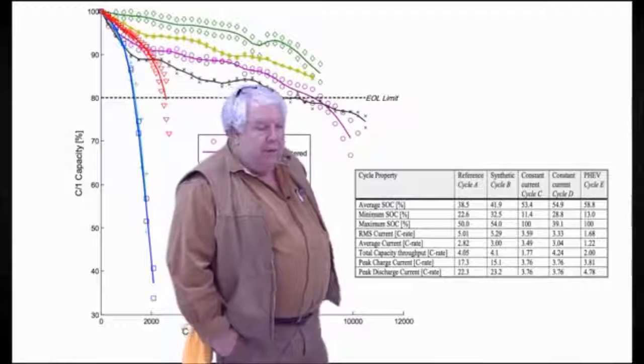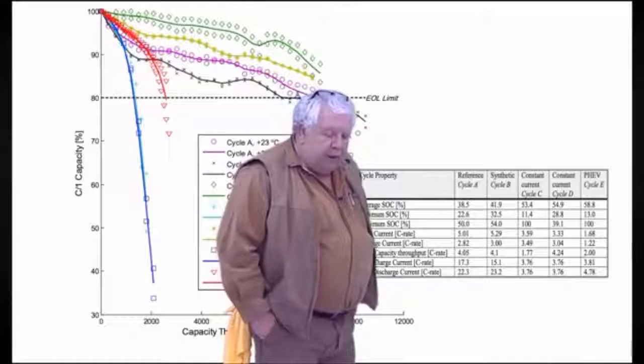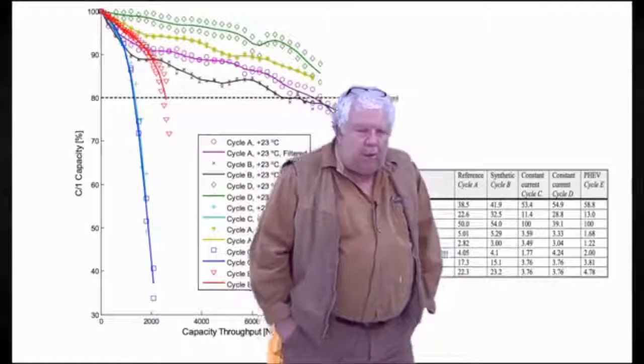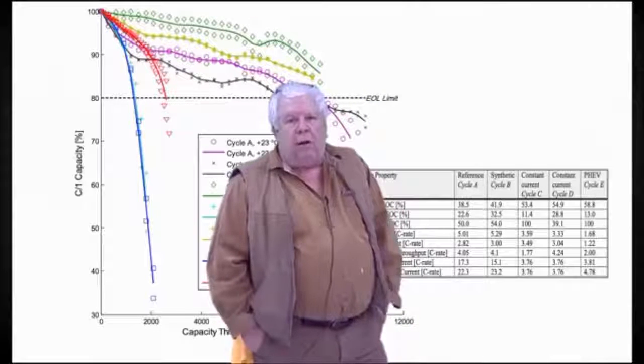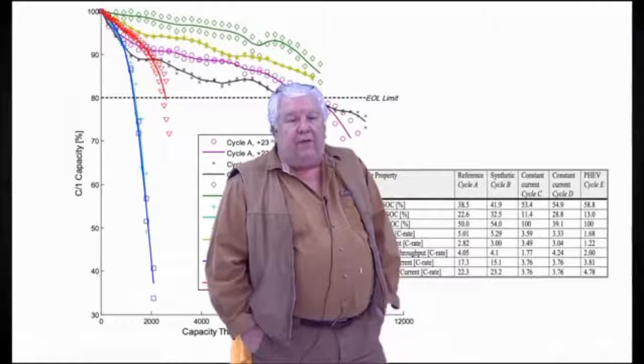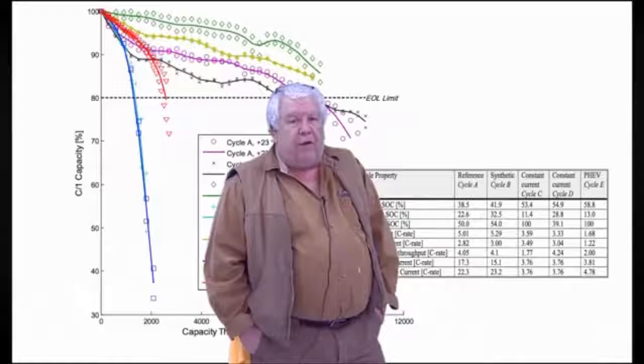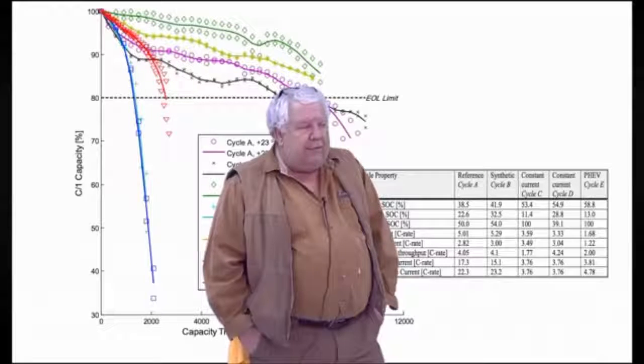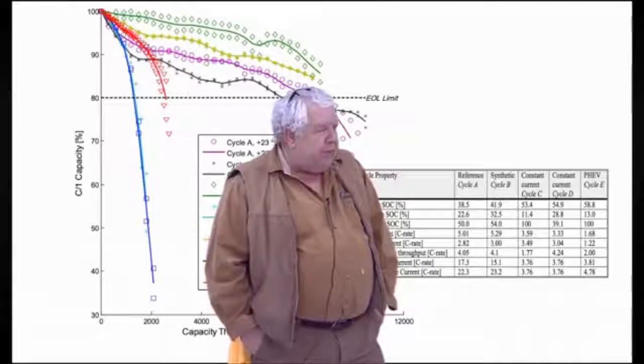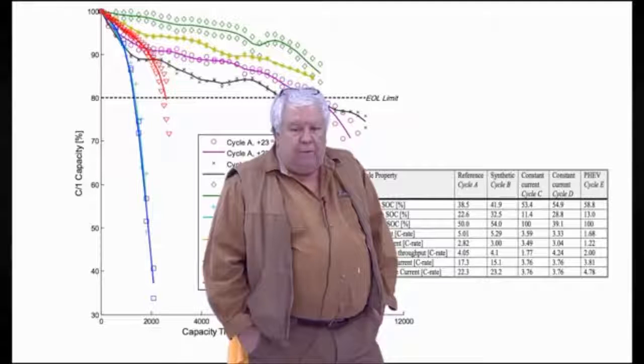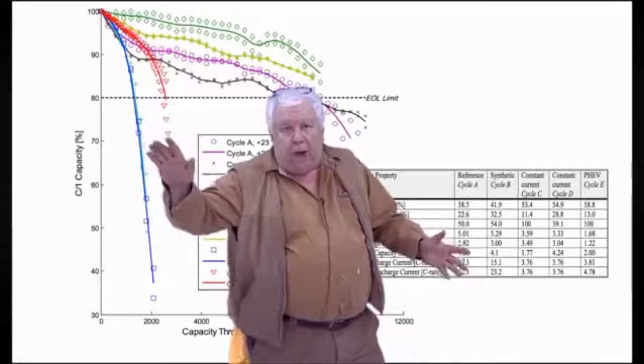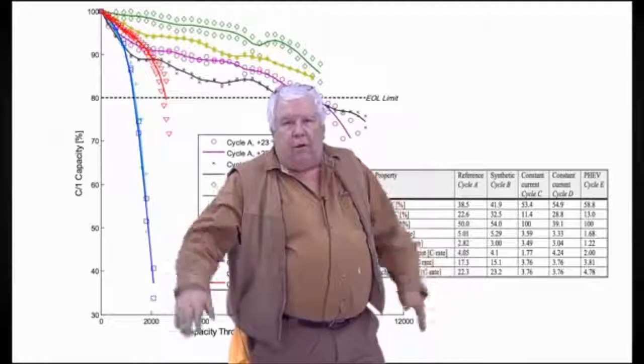And that was the cycle they performed there and had 5 times longer cell life with that, as long as they started at 50% state of charge and didn't go below 22%, that it was fine. And so the biggest determinant of cycle life I would draw from this young man's work is the state of charge, how far you push the limits, the top and the bottom. There's no reason to be there.